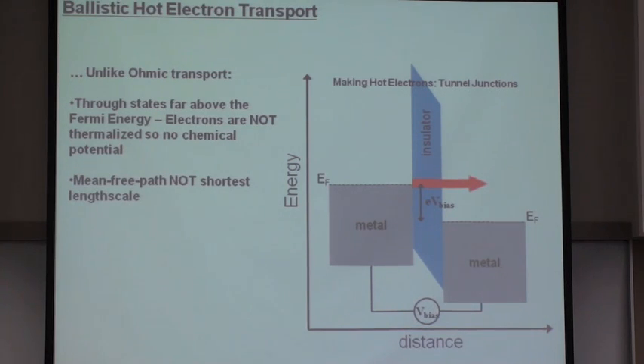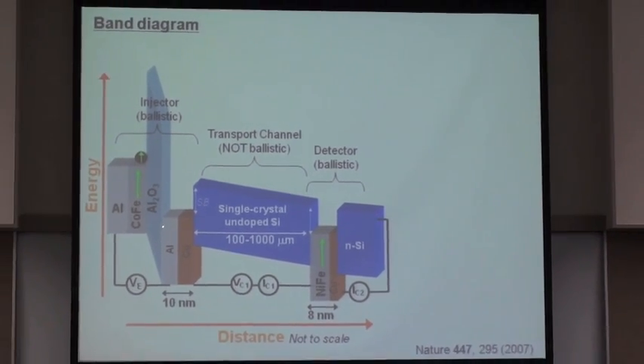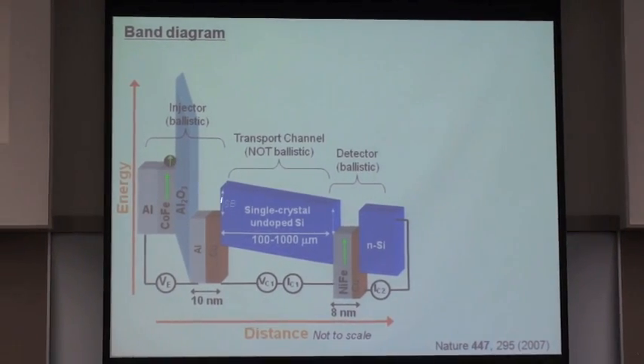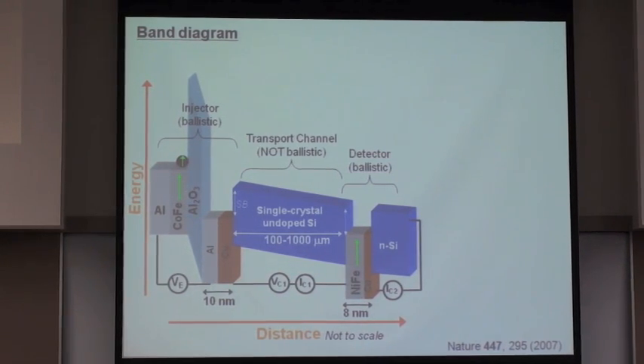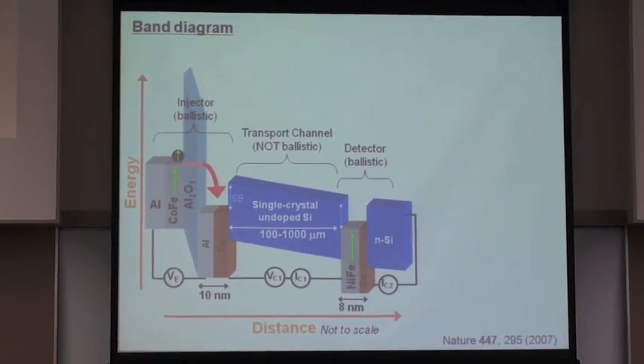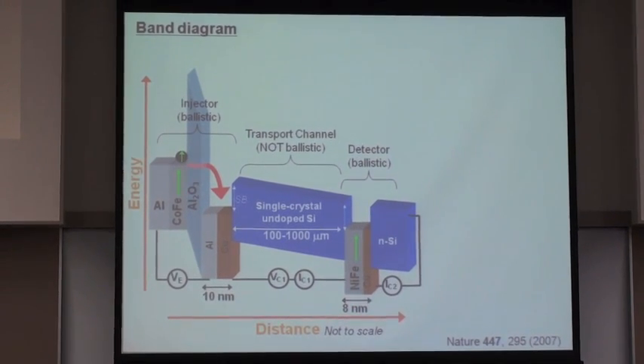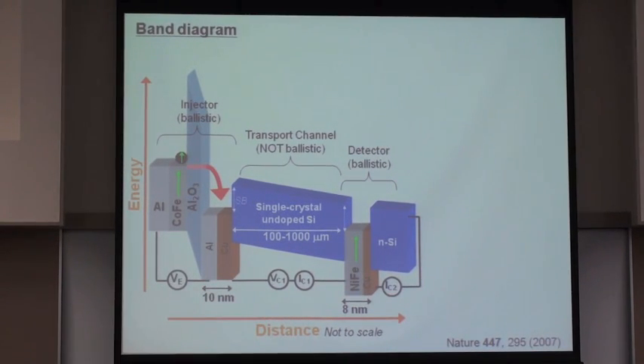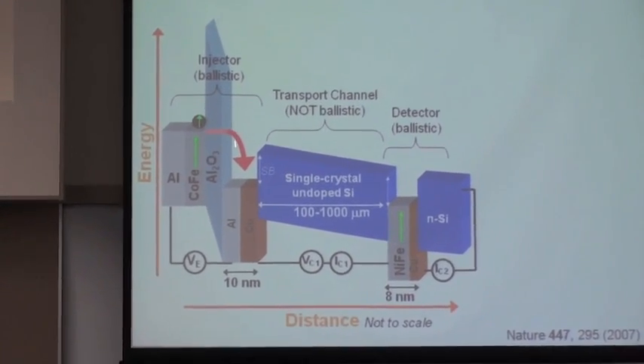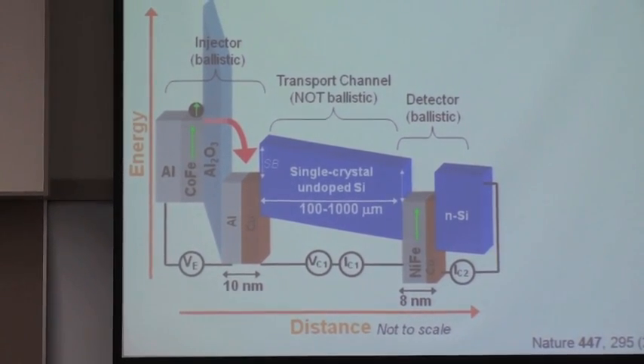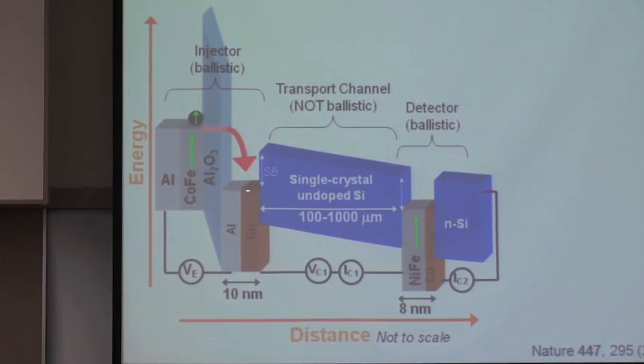How do we do that? Well, we place behind the anode, a thin film anode, a Schottky barrier. The idea being, of course, that if we apply a voltage across our tunnel junction injector, which has a ferromagnetic cathode, we then have more of spin-up electrons tunneling through the barrier. And these electrons couple with hot electron states in the anode. Most of them do suffer inelastic transitions and relax down to the Fermi level, but some of them can move ballistically through the anode, through the non-magnetic anode, and couple with conduction band states on the other side. And that's how we achieve our injection.